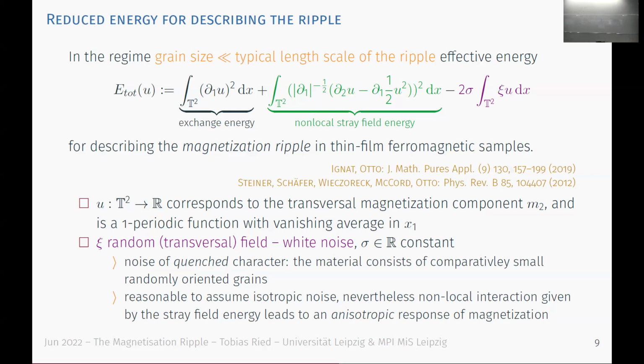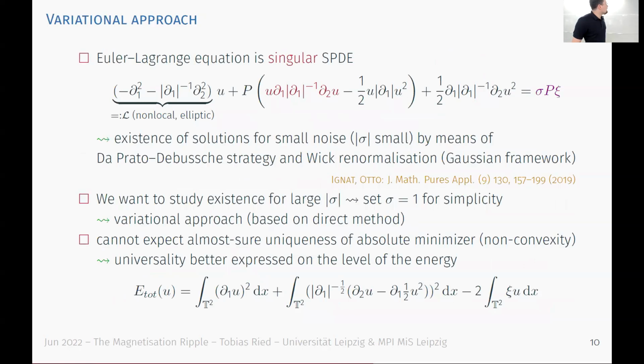Due to the stray field energy, I mean, there's nothing wrong in assuming that the noise is isotropic, but what one sees is that due to the non-local stray field energy, this actually produces some anisotropy. So this leads to an anisotropic response of the magnetization, which has some implications in how we treat it, but let me not go into too many details here, but rather formulate the universality.